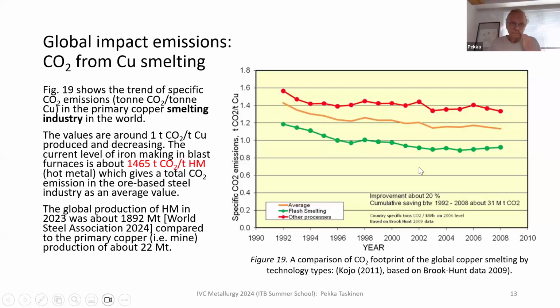And this is less than one ton of CO2 per ton of copper. And just keep in mind that iron making in blast furnaces consumes today about 1,465 tons of CO2 per ton of product, so hot metal, big iron. And if we compare, this is no excuse, but just compare the impact on the global atmosphere.